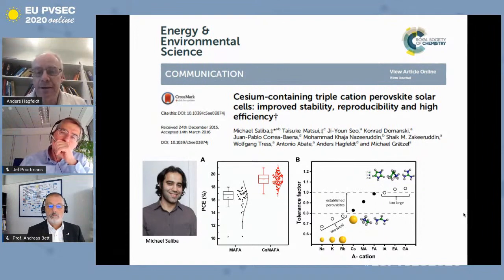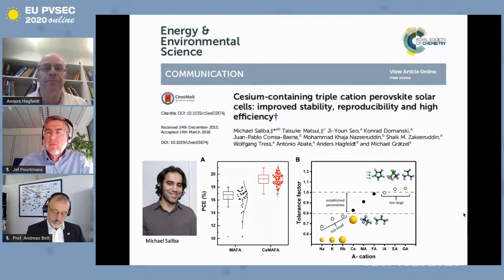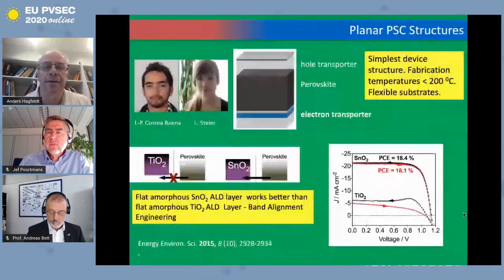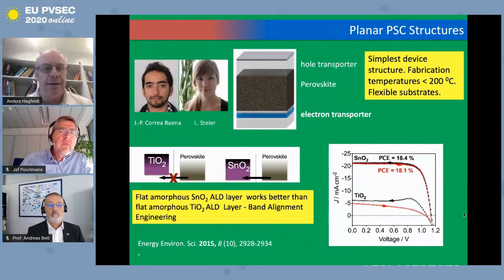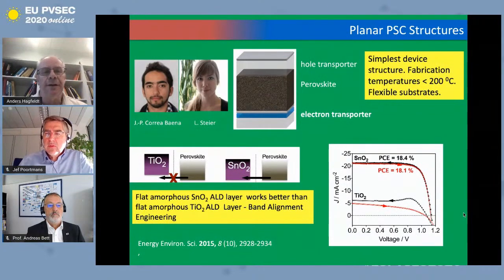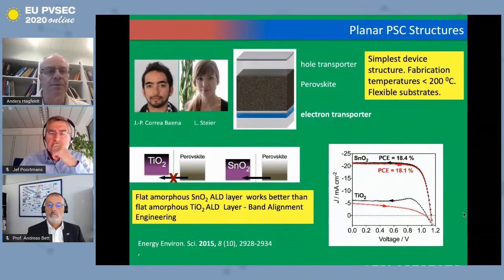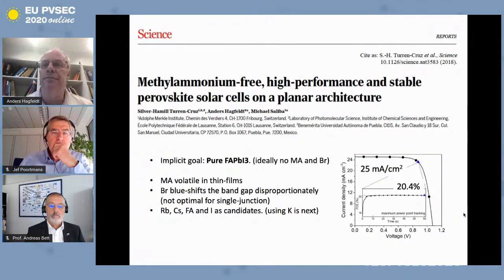And also on the right-hand chart, you can see a little bit on what kind of cations you can think about using, and it has to fit into the tolerance factor, of course. And you see that cesium is a little bit on the smaller size and formamidinium is on the larger size and so on. So this work we have continued a lot with. And another direction we took also some years back was to work on planar structures. This goes back 5 years now, and where we identified tin oxide as our favorite substrate contact for planar perovskite. And this was ALD deposition at the time, 18% efficiency. And of course, now there is a lot of work on both mesoporous, and it's normally TiO2, and also on tin oxide. A combination of these two directions we published 2 years back now.